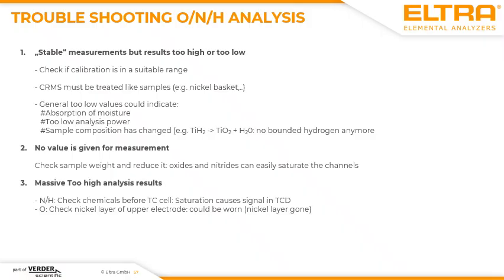aggressive to the nickel layer on the upper electrode, which means when this nickel layer is removed, the crucible will get in direct contact to the mass of the upper electrode, which means the copper which is inside the upper electrode is analyzed directly, and this could cause a very high oxygen content.